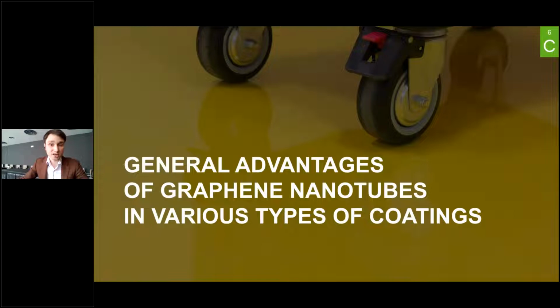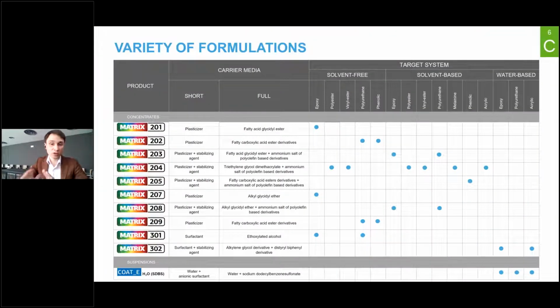And let's sum up some general advantages of single wall carbon nanotubes. First of all, it is easy to work with them. To be honest, you don't even need to disperse pure single wall carbon nanotubes at all, because you will get from our side a masterbatch. We produce concentrates, which are pre-dispersed single wall carbon nanotubes in some carriers. These additives usually contain only 10% of carbon nanotubes and 90% of the carrier, which is compatible with your